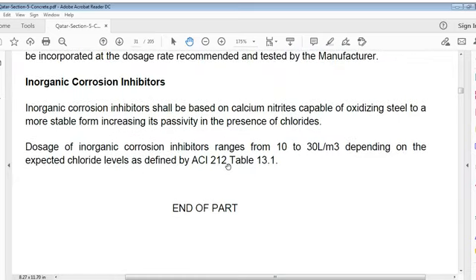Inorganic corrosion inhibitors. Inorganic corrosion inhibitors shall be based on calcium nitrite. Very important point. Inorganic corrosion inhibitor is very important. Practically, it's done in piling particularly. Inorganic corrosion inhibitors shall be based on calcium nitrite, capable of oxidizing steel to a more stable form, increasing its passivity in presence of chlorides. Doses range from 10 to 30 liters per meter cube depending on expected chloride levels defined by ACI 212 table 13. So 10 is minimum. Calcium nitrite we have to add in piling particularly, or it can be added to foundations also.